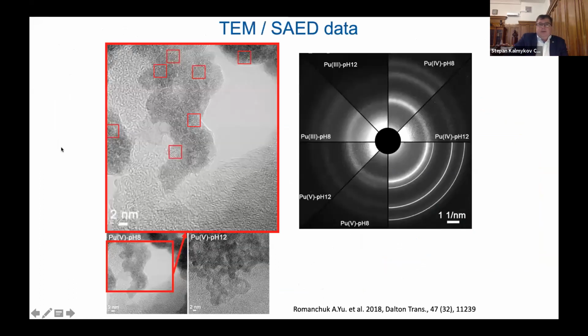So first it was seen by TEM that there are a lot of very small nanoparticles, so we can see their crystallinity. The size is about 2 nanometers. According to the selected area electron diffraction, we can see that these are plutonium O2-like particles that are formed.